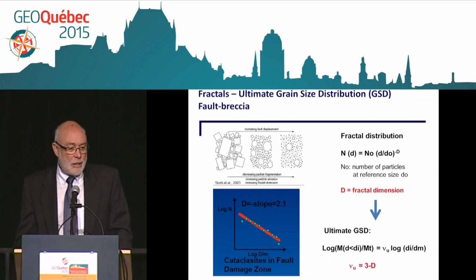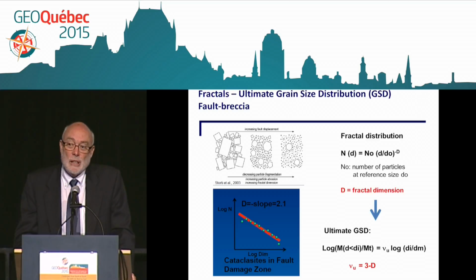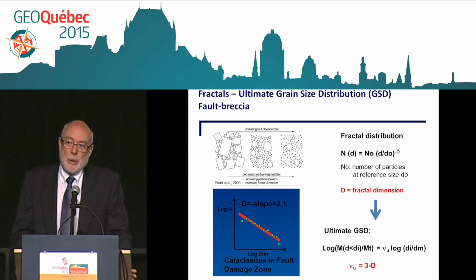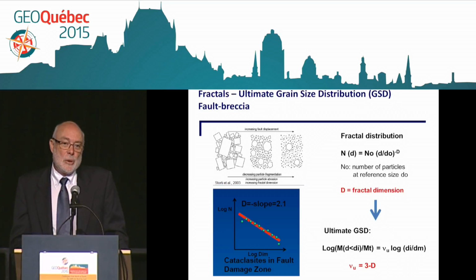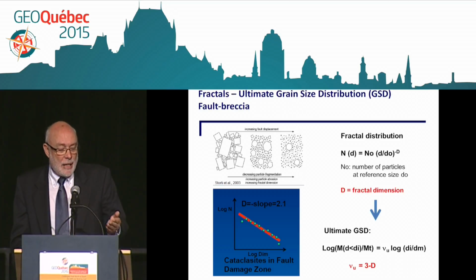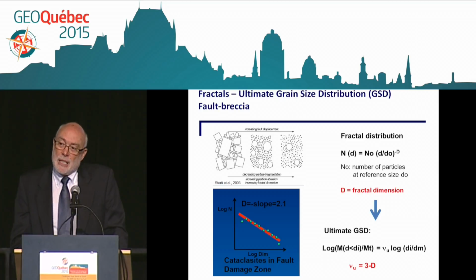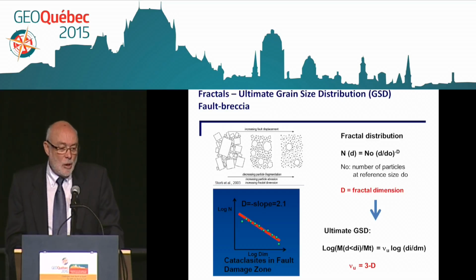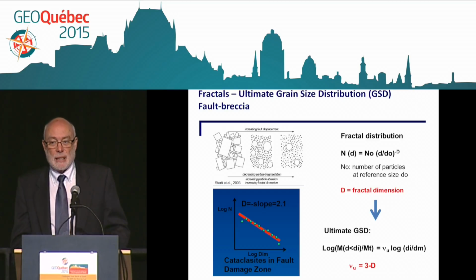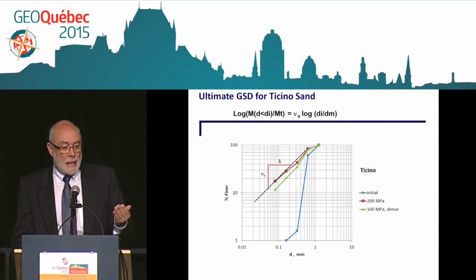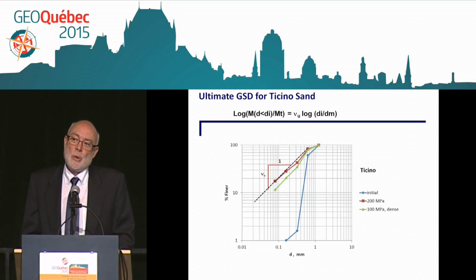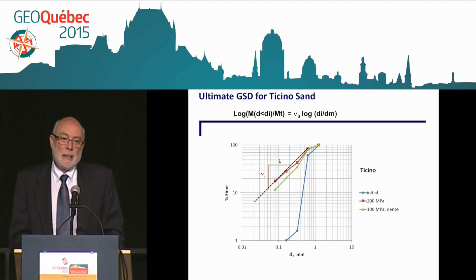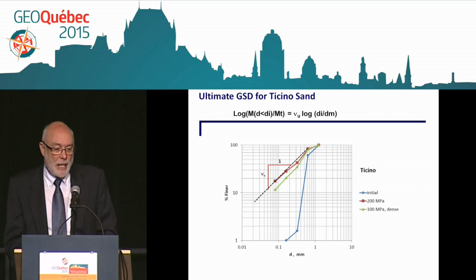And another such observation was done along faults. When the fault is moving, the shear stresses induced during the movement will actually break down the rock structure, and finally come to that fractal distribution that is characterized in a log-log distribution by the slope of that relationship between number of particles and size of particle. So this is what we then chose to use for defining the ultimate grain size distribution during crushing or fragmentation.